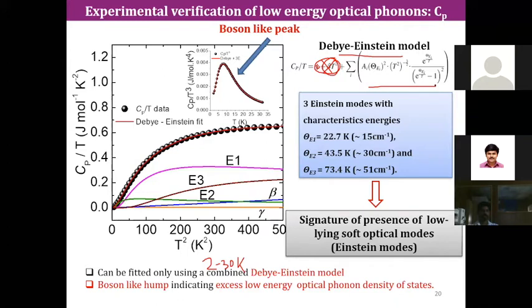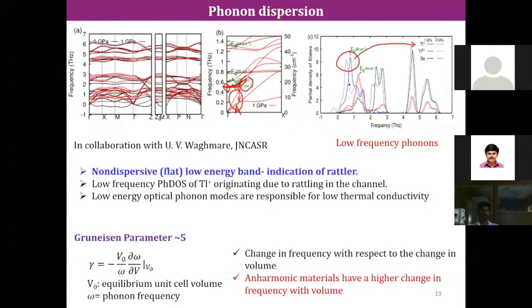So what Einstein assumed, basically, in a Debye solid, Einstein assumes a single atom as a rattler. So this rattler mode we can estimate from this low temperature heat capacity data, which is ultra low energy, around 15, 30, or 51 centimeter inverse, which was calculated by theory as well. So this is in that terahertz, basically in the same region, only the unit is different.